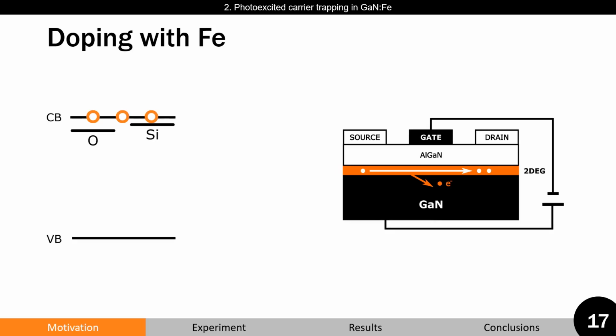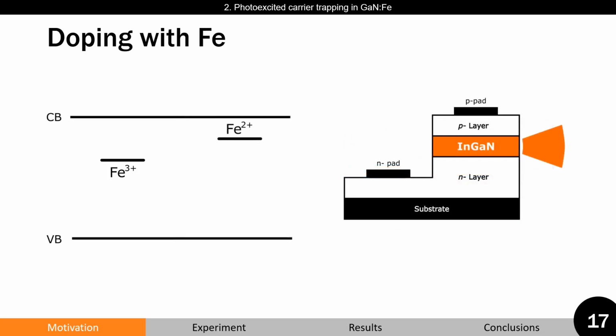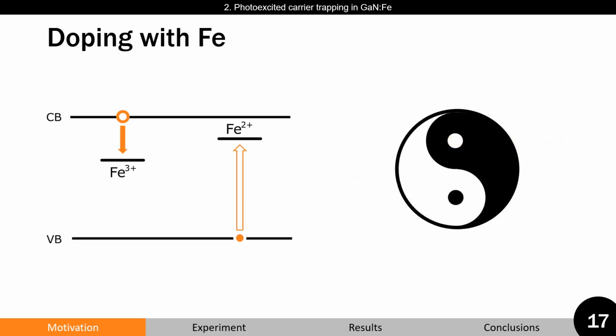One of the methods to solve this is intentionally doping gallium nitride with iron, which introduces deep acceptor states and allows us to fabricate semi-insulating layers. On the other hand, iron could be introduced unintentionally. Having deep states in the band gap might lead to efficient non-radiative recombination rates, which would be detrimental for optoelectronic device performance. For this reason, in order to evaluate both positive and negative aspects of doping with iron, carrier trapping